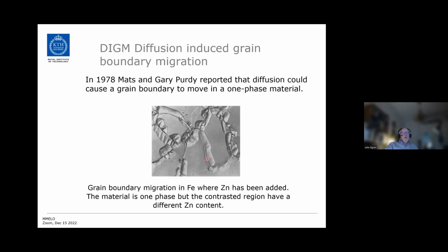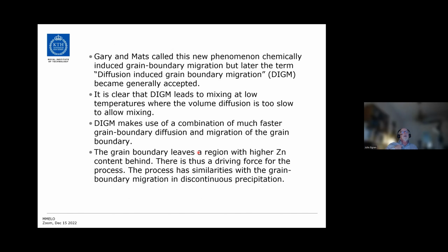So here is a micrograph, and here is the initial pure iron, and these regions where the grain boundary is now, and this region which is left behind the grain boundary, they have a high zinc content. And they called this new phenomenon chemically induced grain boundary migration, but later the term diffusion-induced grain boundary migration became generally accepted. So one can notice here that DIGM leads to a mixing at low temperatures where volume diffusion is too slow to allow mixing.